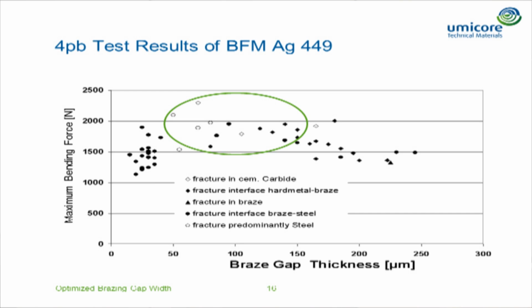So now we come to the results. First we look at the results for the normal brazing filler metal without any sandwich in between. And these are the results here: on the x-axis we have the different gap sizes we found out after the tests, and here the maximum force we applied onto the part.